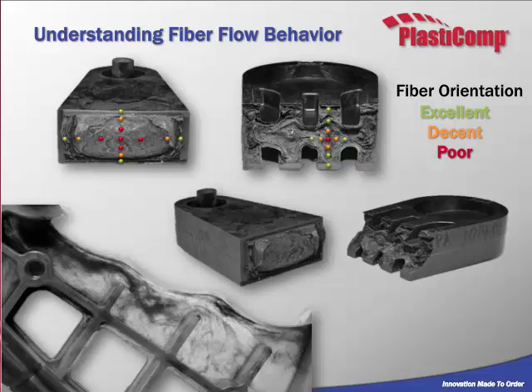so you're not maximizing your strength on the red dots. Now, looking back at this connecting rod with that in mind, you can see that the thick part had excellent fiber orientation towards the walls, but as you go to the center, you quickly realize that the fibers start tumbling, and a majority of the thickness of your part isn't utilizing your fiber strength as much as it could be.